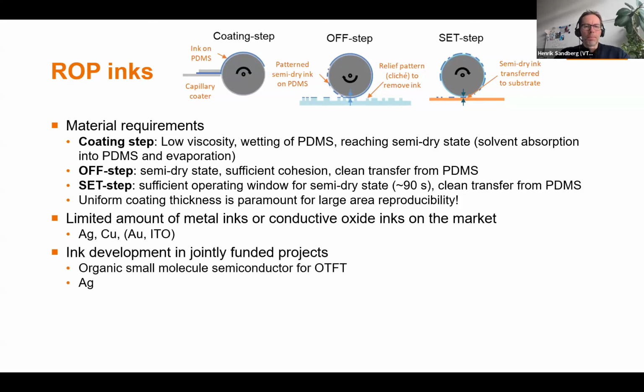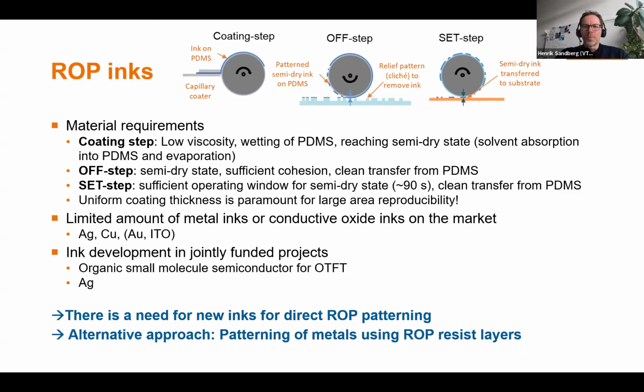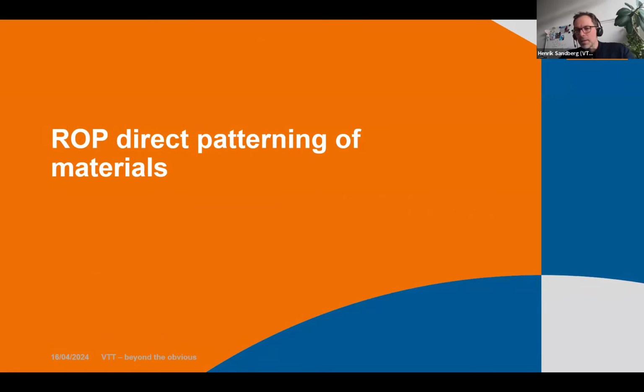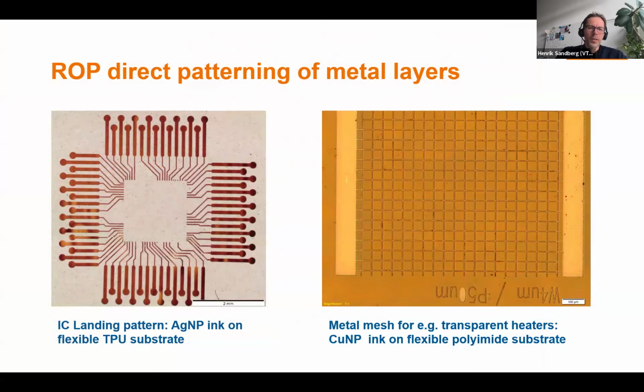And then we have some semiconductor material based on both organic molecules and also on metal oxides. And then there are polymers you can print with this method. So we see this as a good way forward to reach high quality electronics by printing. If we don't have a suitable ink, we can always do patterning with this method, and that is the last part I will talk about with this method, that you print a pattern, and then with a material that works well with the process, and then you apply the material you want patterned, and then you do a lift-off process.